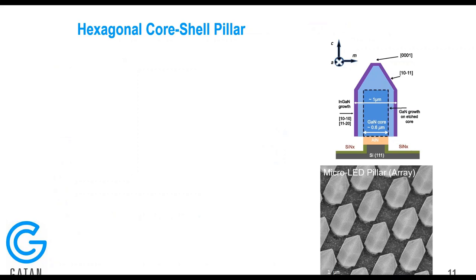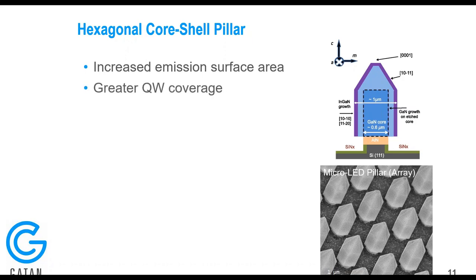In particular, researchers are looking towards pillar type designs in order to improve the emission properties of micro LED arrays. So in this case, we look at a hexagonal core shell pillar, which has indium gallium nitride on the outside and a gallium nitride core. The reason we go to this pillar structure is that we have an increased emission surface area as opposed to a 2D structure, which would just have the area on an XY surface. So here we go in the Z direction as well. This also has the benefit of having a greater quantum well coverage. So the entire surface of this pillar is made up of a quantum well.